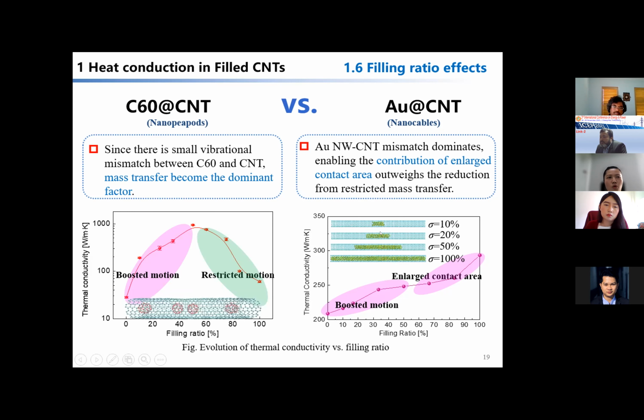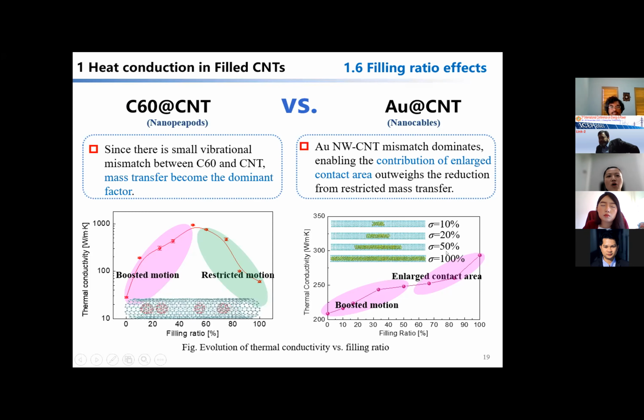Different from the nano-peapod, the thermal conductivity of nanocables always increases with increased filling ratio, primarily because the contact area between the gold nanowire and the tube enlarges. That is, gold nanowire, sorry, not a particle, gold nanowire. The gold-tube mismatch dominates, so the contribution of the enlarged contact area outweighs the reduction from restricted mass transfer. Of course, similar to the peapod, when not fully filled, the filler, the gold nanowire, would be in translational motion, which induces mass transfer and increases the energy transportation.